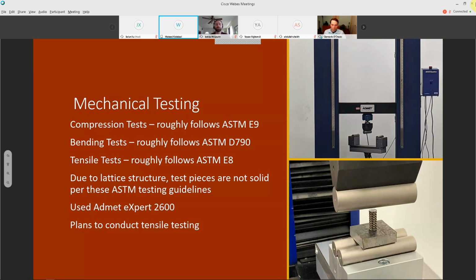Shown on the top figure is the mechanical testing machine that we used, called the Admet eXpert 2600. It is located on campus in Building 42. The bottom figure shows the setup of our compression test. As you can see, our compression specimen is installed under the inline fixture. Although this is a bending fixture, and a platen fixture would be more recommended for this compression test, we used the tools that were available at the time to minimize delays and costs.